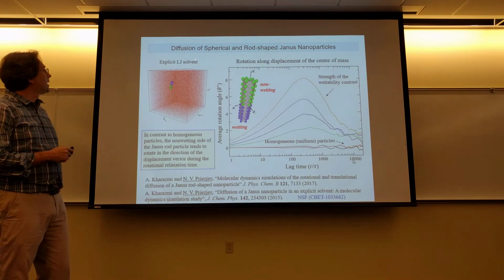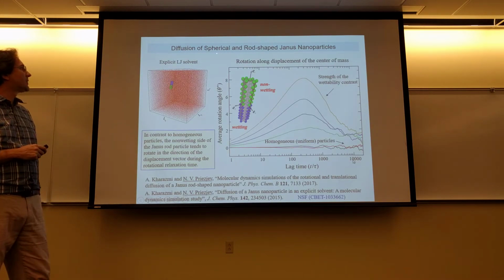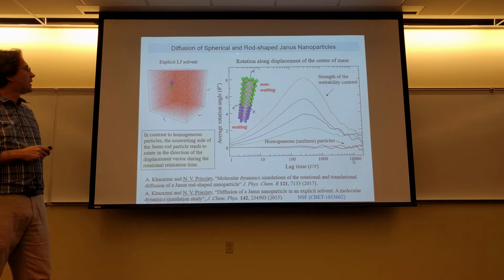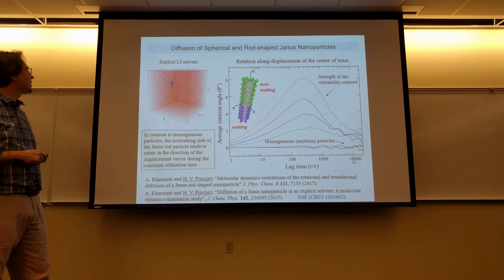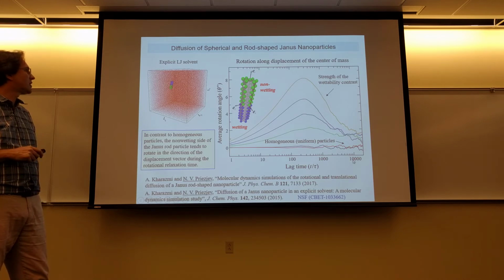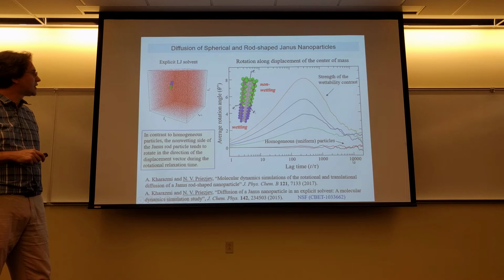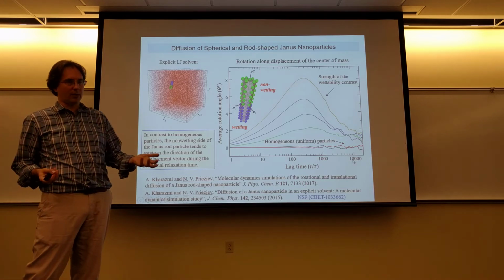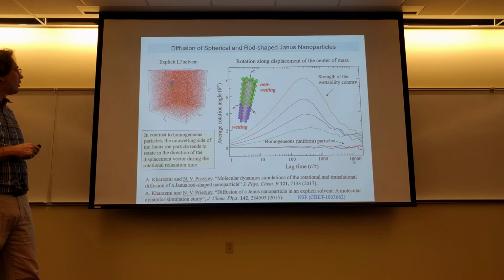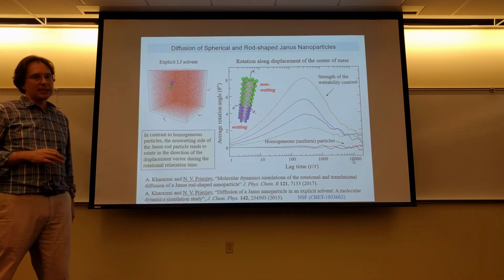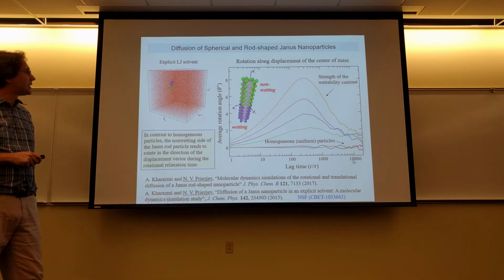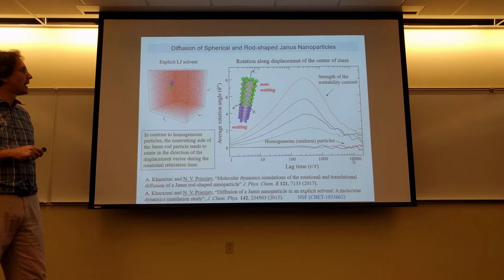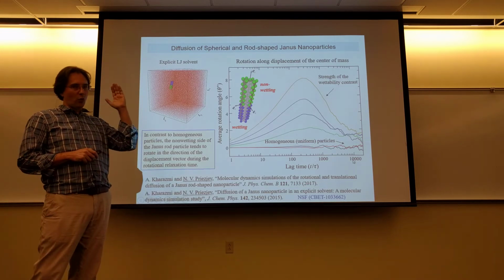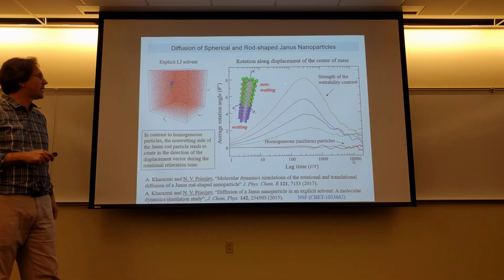Good. And then the third one on the fluid side deals with diffusion of either spherical or rod-shaped Janus nanoparticles, which are immersed in Lennard-Jones solvents. In this situation, we have a nanoparticle that's constructed in such a way that one part is non-wetting, it doesn't like liquid, and the other part is wetting, it likes liquid. It turns out that diffusion of such a particle in a solvent is peculiar. Namely, under spontaneous motion of the center of mass, the non-wetting side of this particle will be oriented towards this displacement to reduce drag.